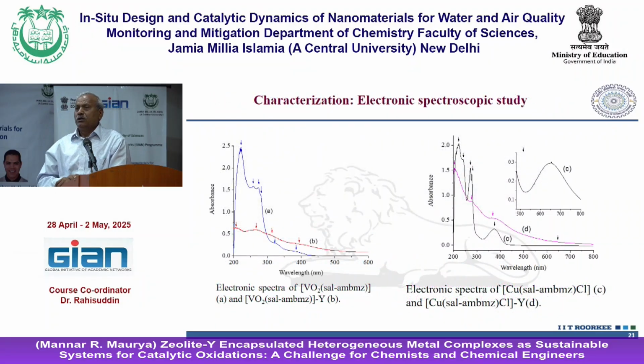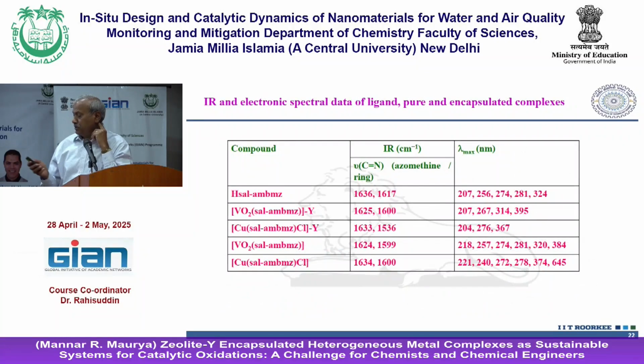The other thing is electronic spectroscopy, that is helpful sometimes, but again how to record the electronic spectra? What I told in the morning: grind it in nujol nicely, make it like a suspension, emulsion type, attach the paste in the cuvette in one, and in the other one make nujol the reference, you should be able to record it, and sometimes we get good information out of that. So if you have a charge transfer band, you should be able to see that. If you have bands due to organic moieties, transitions like n to pi star and pi to pi star, you should be able to see that. And sometimes if you have unpaired electrons, then d-d bands you can also see. It's very possible. Okay, so that can be characterized. So IR is listed here and UV-visible is listed. You should be able to see that.